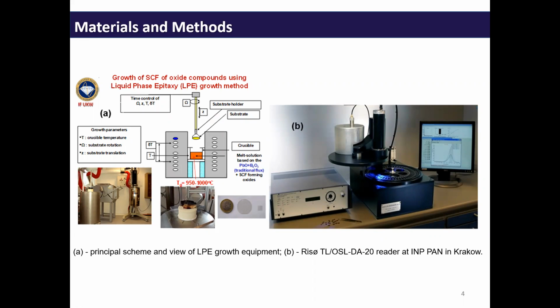For characterization of the luminescent properties of the single crystal film and single crystal parts of the composite detector under high energy excitation, the cathodoluminescent spectra of SC and SCF parts of the composite detector were measured using a SEM JEOL JSM 820 electron microscope with additional equipment with a StellarNet spectrometer working in the 200 to 1100 nanometers range. For TL measurements, we use the Risø TL reader under alpha and beta particles excitation by 241 americium and 90 strontium sources, respectively.